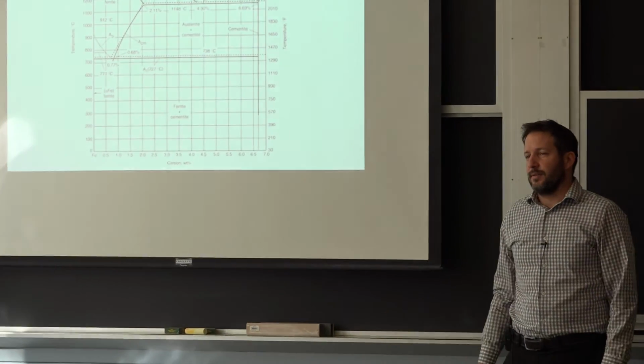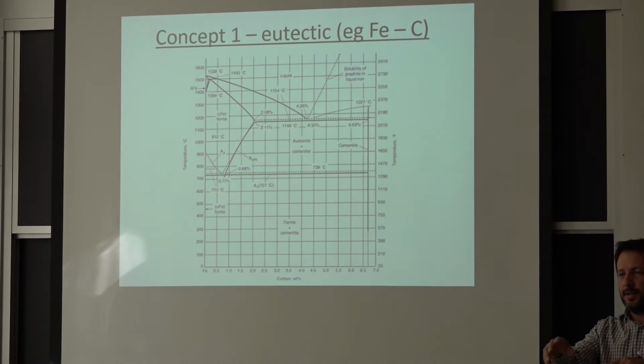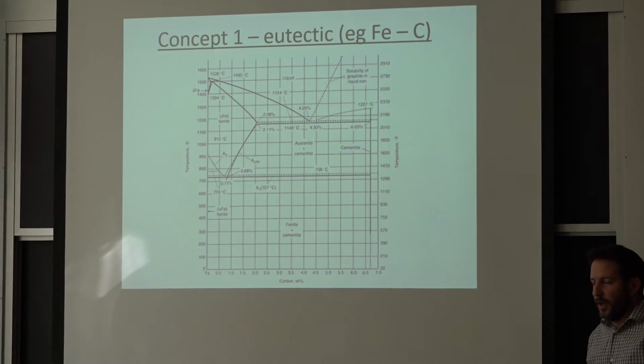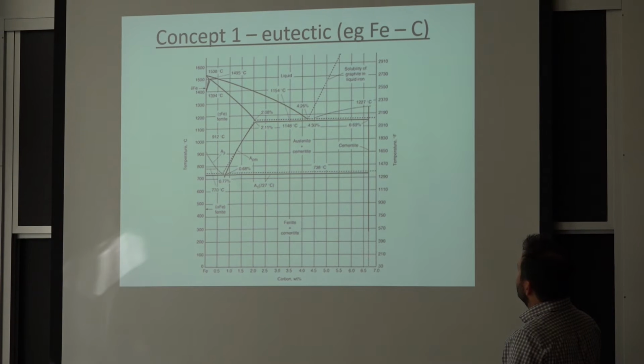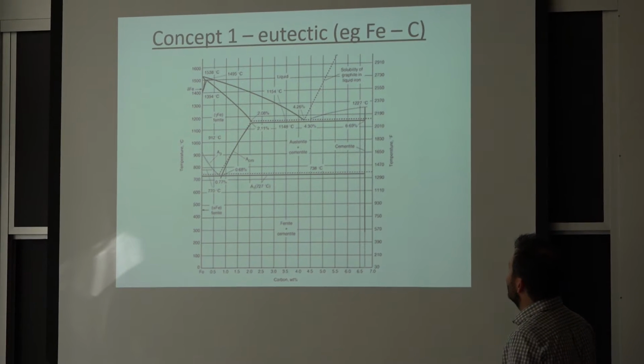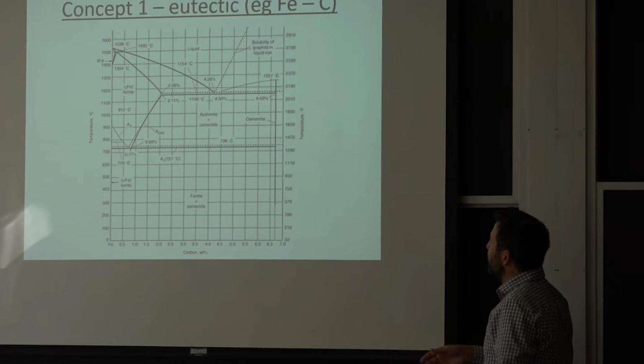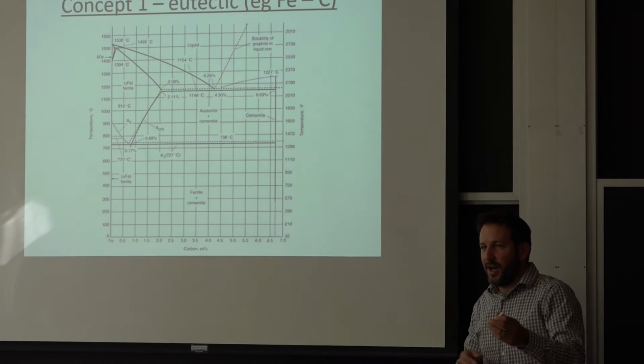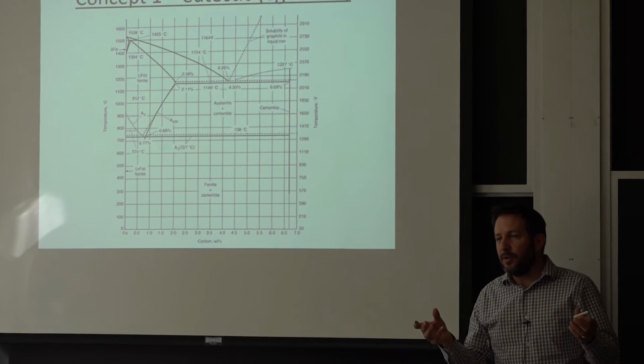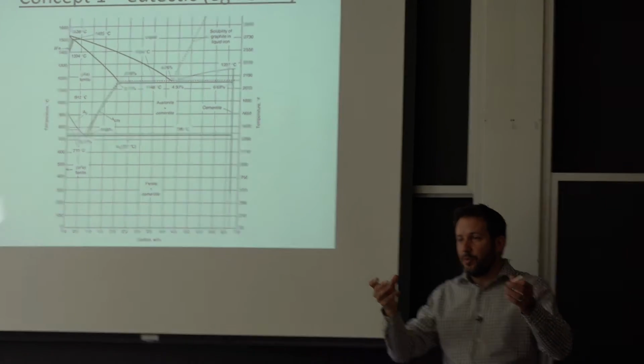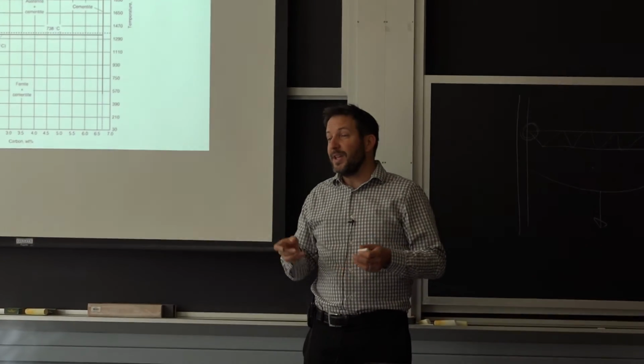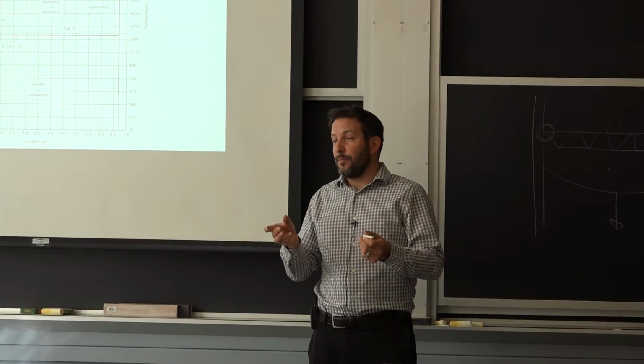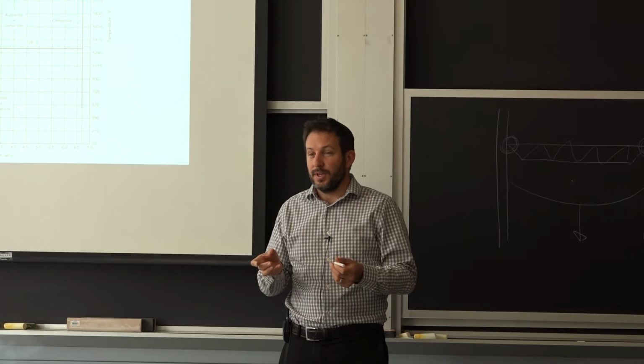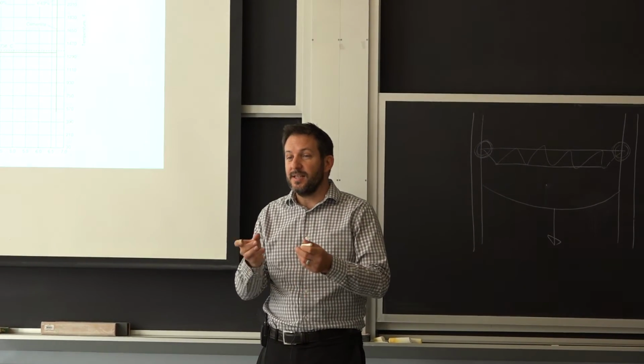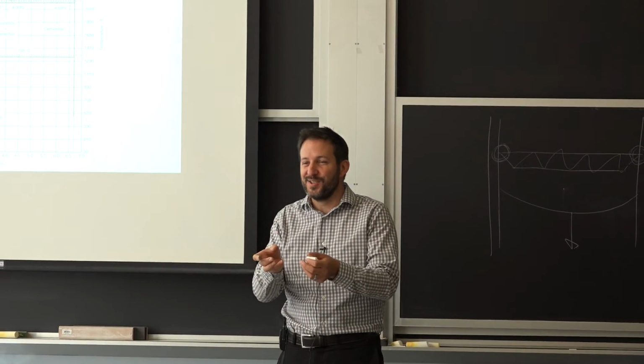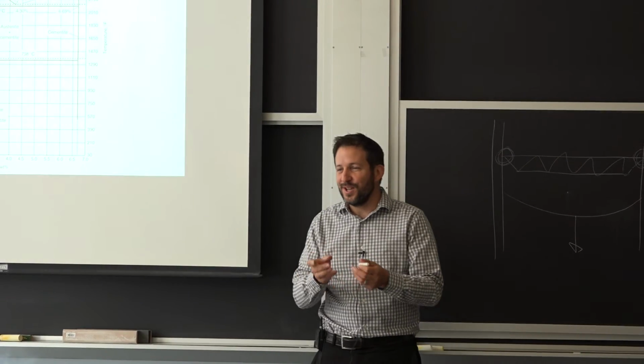They like each other. The carbon just goes around and it just looks like water. When you start cooling down, well, the melting point of carbon is a lot higher than iron. The two of them together, you can keep them liquid to a lower temperature. Well, that's awesome, because the first thing you want to do if you're going to cast something is heat up as little as you possibly can. This is really, really hot.